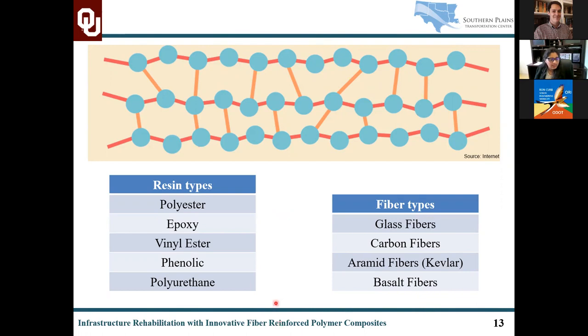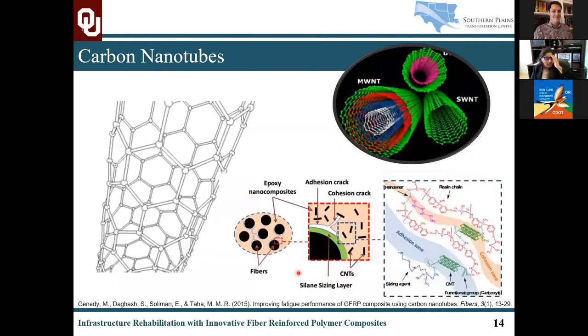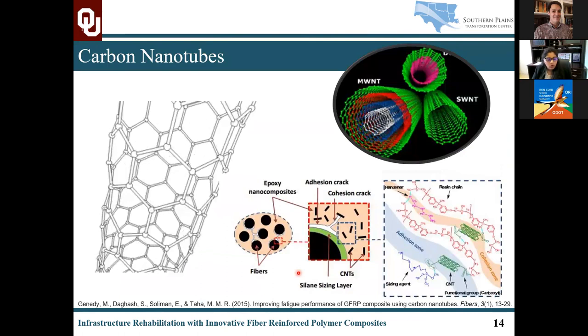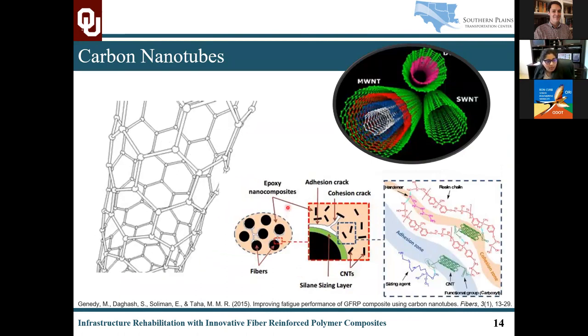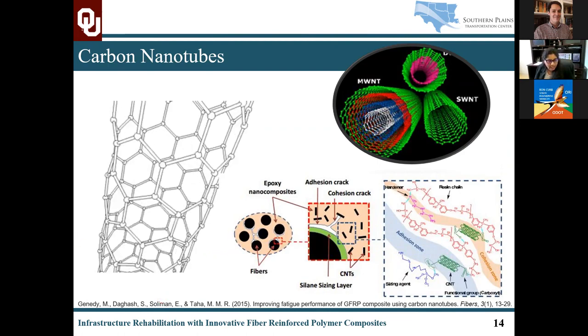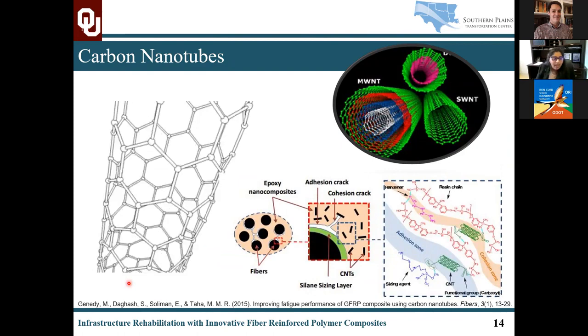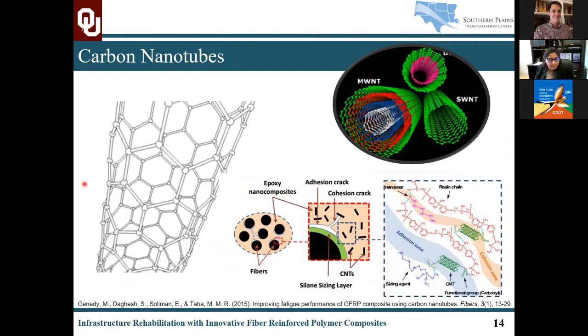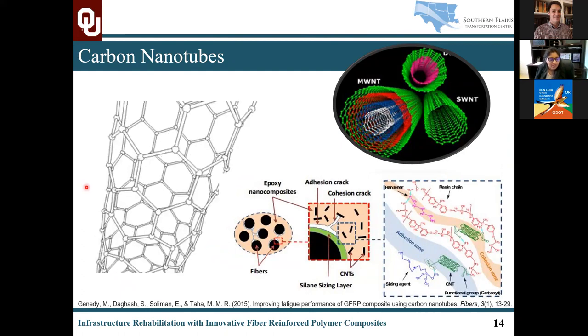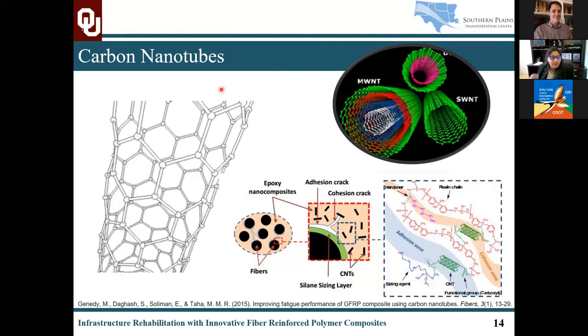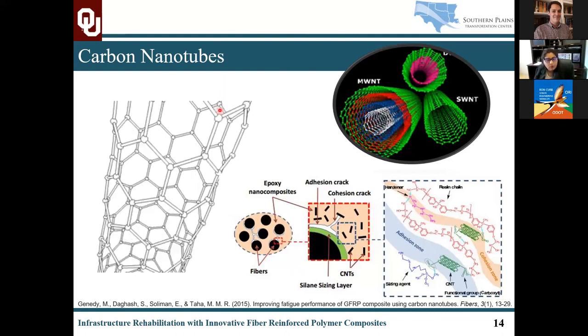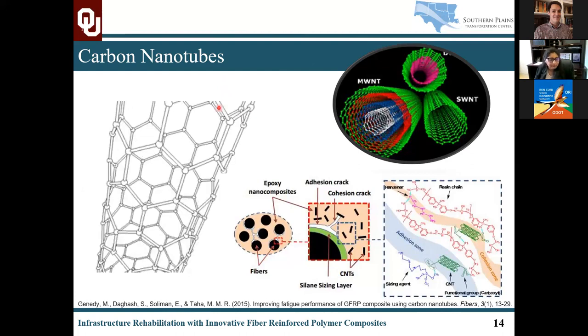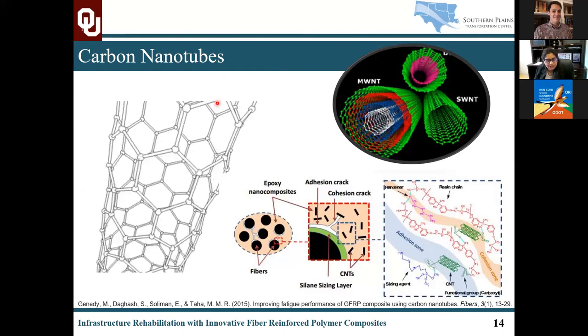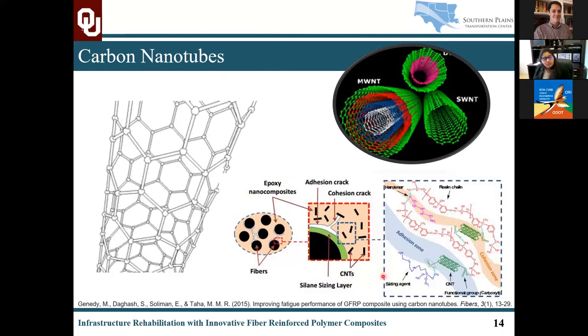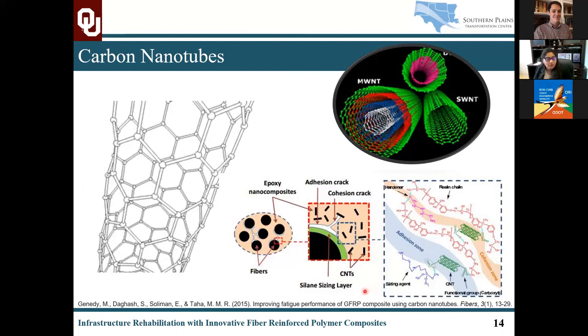Different resin types and different fiber types are usually combined, but looking particularly at nanomodifications, carbon nanotubes stand out when we talk about nanomodified resins. Carbon nanotubes can be pristine or functionalized with different kinds of functional groups. I have worked with carboxyl functional groups particularly, and looking at the results of different resin modifications with these carbon nanotubes, the carboxyl functional group improves the bond between glass fibers and epoxy. Potential chemical reactions improve the adhesion strength, bond strength, cohesive strength, and shear strength of the fiber matrix interface.